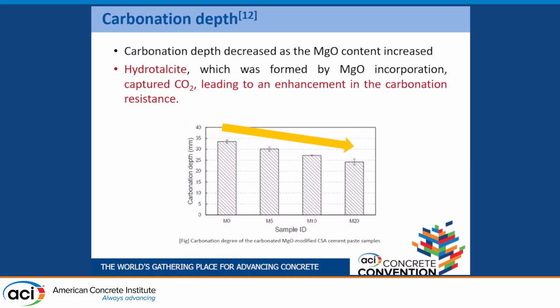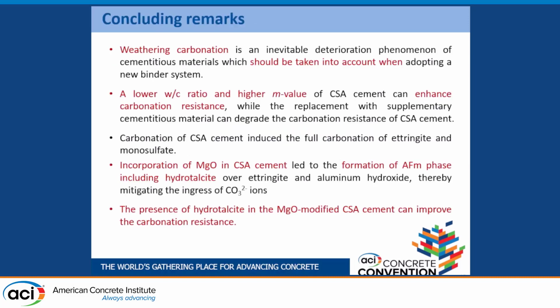This is the final slide of my talk. These are the carbonation depth results based upon the phenolphthalein indicator test. The results show that the incorporation of magnesium oxide decreased the carbonation front, and as we expected, the hydrotalcite formed by magnesium oxide incorporation captures CO2, leading to an enhancement in the carbonation resistance. So these remarks conclude my presentation.